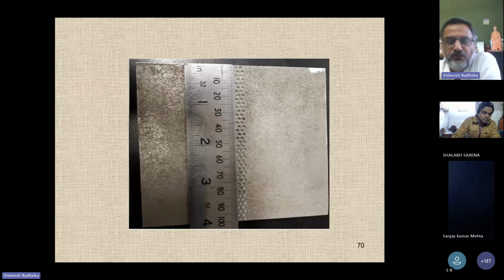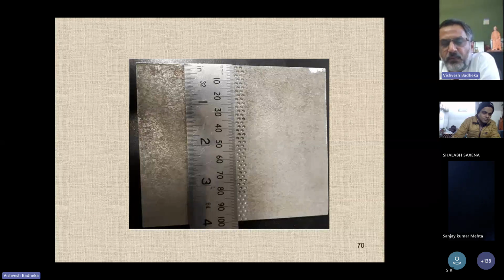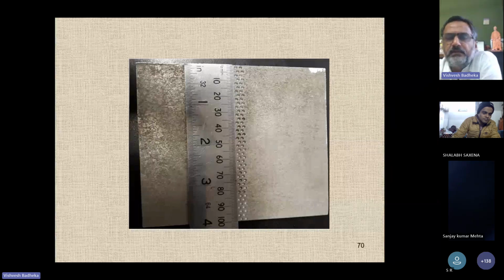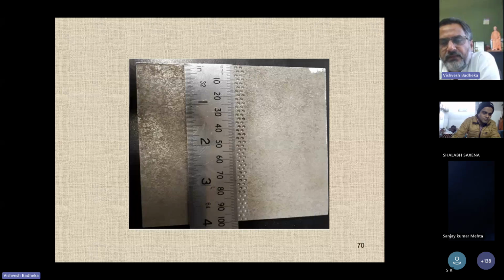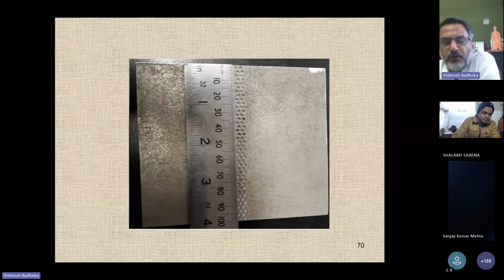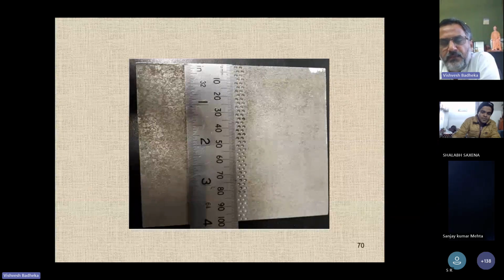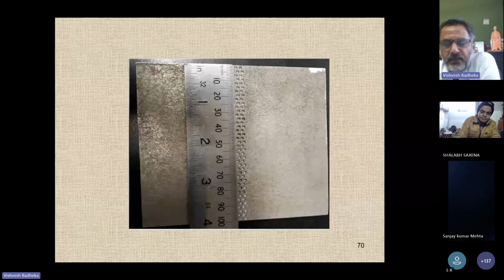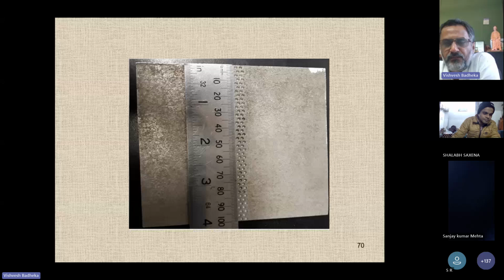How much volume fraction you are adding here is also very, very important, because finally the property will be governed by the volume fraction which is added during the process. So these holes will be filled with the reinforcement, and then you apply a capping pass, then a stirring pass, and the number of passes is also a parameter. In the same area you can do stirring 1 time, 2 times, 3 times, either in the same direction or in the opposite direction, so that you can ensure better mixing of the reinforcement into the matrix material.